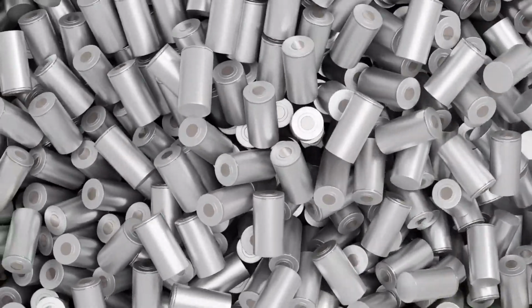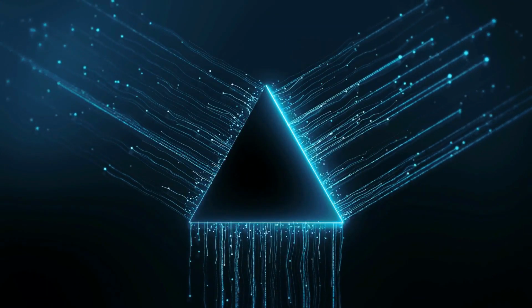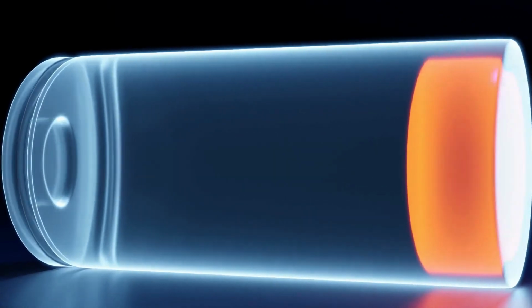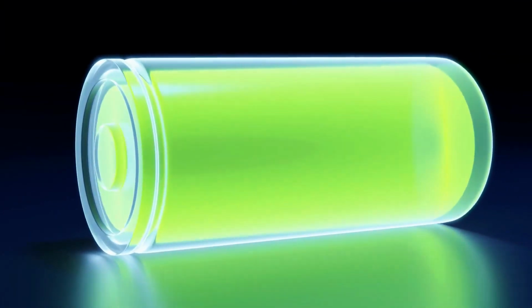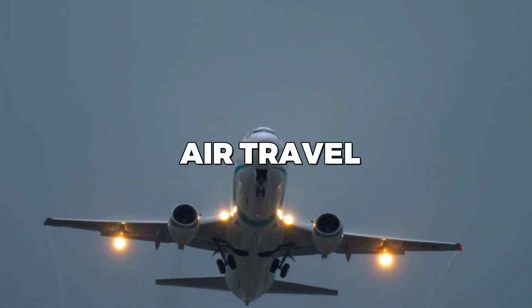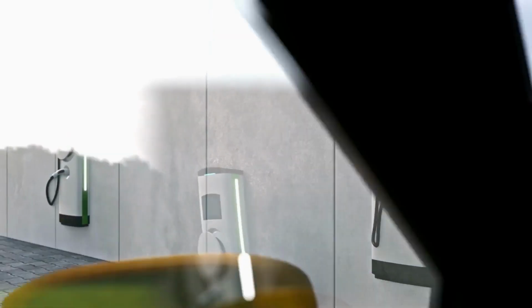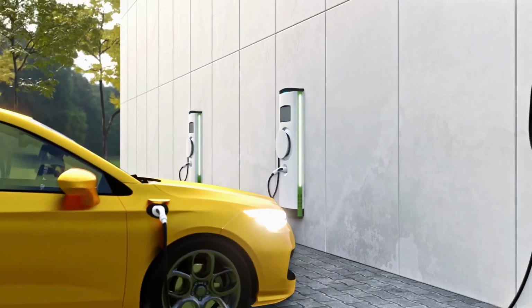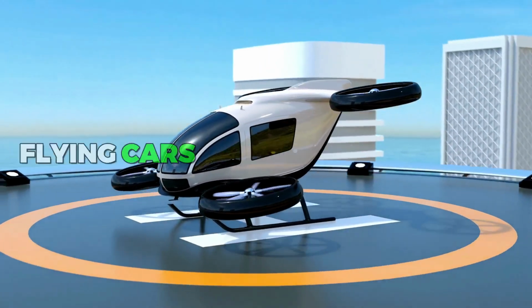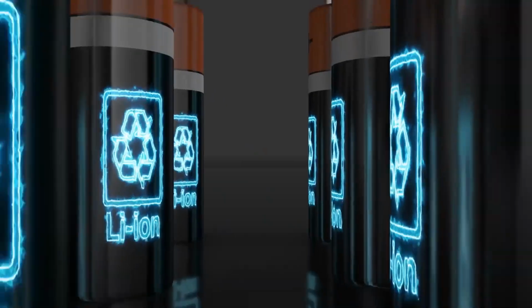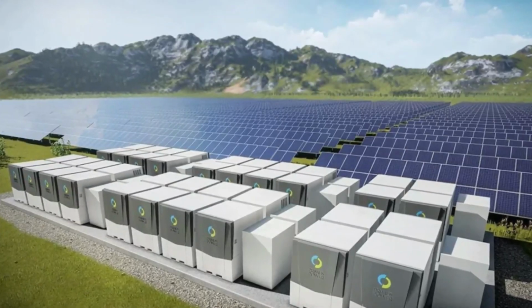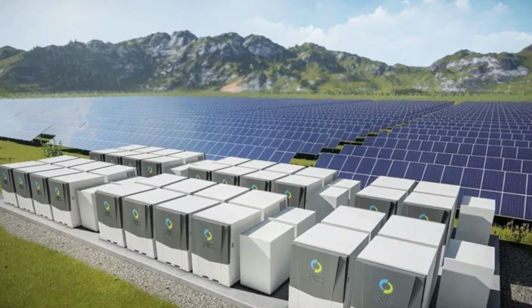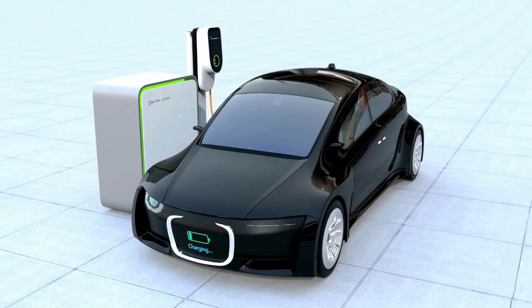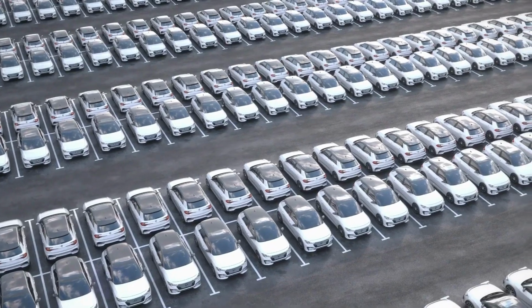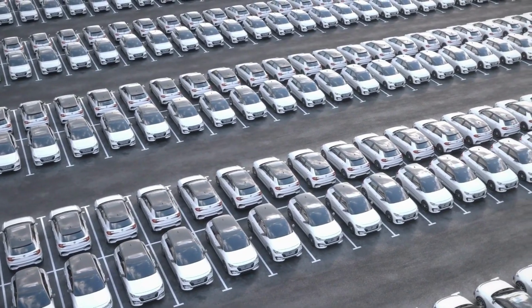This video discusses the remarkable evolution of battery technology, focusing on the advancements made by Amprius Technology. Their high-energy dense battery technology, reaching an incredible 500 watt-hours per kilogram, promises to revolutionize air travel and the aviation industry. The battery's fast charging capabilities, increased EV ranges, and potential to power flying cars make it a game changer in the industry. The video also delves into the technical aspects of the battery, explaining how Amprius has replaced the usual graphite grid with silicon nanowires in the anode, allowing for more lithium storage and extending cell life. The structure of the silicon nanowire anodes enables extremely fast charging capabilities, doubling the flight time of eVTOLs and significantly increasing the range for electric cars.